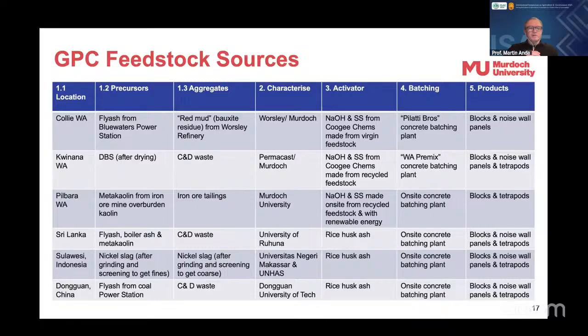Actually, this is something I'm interested in for Sri Lanka as well, because I understand that there are some kaolin deposits there, which is used for the ceramics industry, and so we can convert the kaolin into metakaolin at about half the temperature that you normally use for Portland cement, and so 750 degrees instead of 1500 degrees, and that we can make a geopolymer in Sri Lanka from either the fly ash from the coal power station or with the metakaolin, and then for aggregates we could use C&D waste if we wanted to avoid the use of virgin sands and aggregates. But interestingly, in Sri Lanka, Indonesia and China, where I'm working, we can use rice husk ash to make the sodium silicate. So there's interesting opportunities in all of these different places.